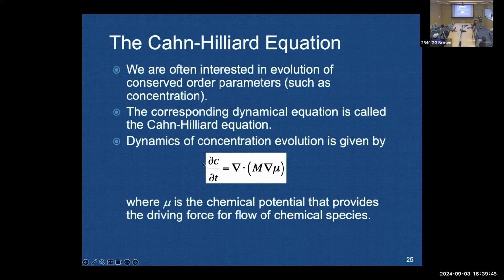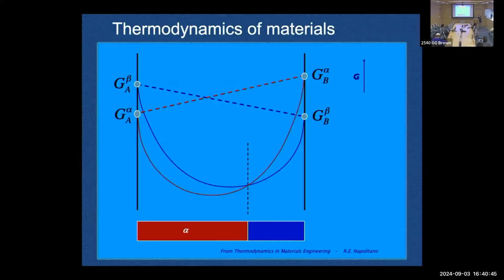If you look at this, dC/dt equals the gradient dot M grad mu, it looks like a diffusion equation, except you have mu here, which is chemical potential. Usually when you see a diffusion equation, you see D over here and then C over here. But that only works if you have an ideal system, unless of course you make D take into account the changing chemical potential with respect to concentration. But this is really the generalized diffusion equation, and you can solve this equation to figure out how the system is going to phase separate. I don't have a lot of time, but this is where the chemical potential comes in.